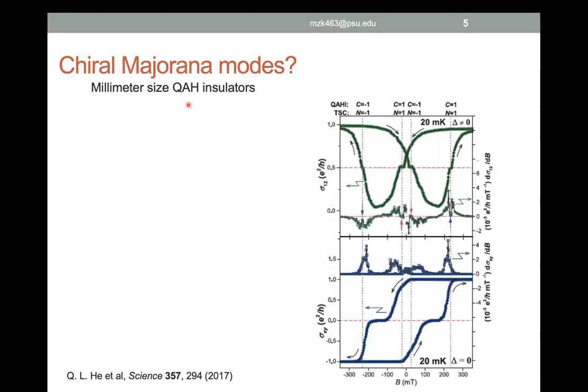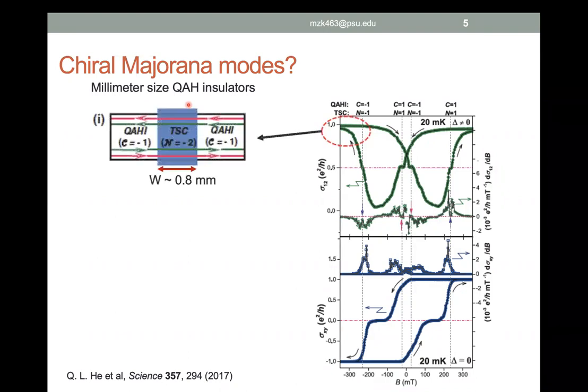Let's take a quick look at what they had reported at the time. I need to mention that this paper was recently retracted by an editorial retraction. Nevertheless, we're just going to look at what they had reported here. In a quantum anomalous sample such as the one shown here with a niobium superconductor, the width of the superconductor deposited on top of it is 0.8 millimeter.